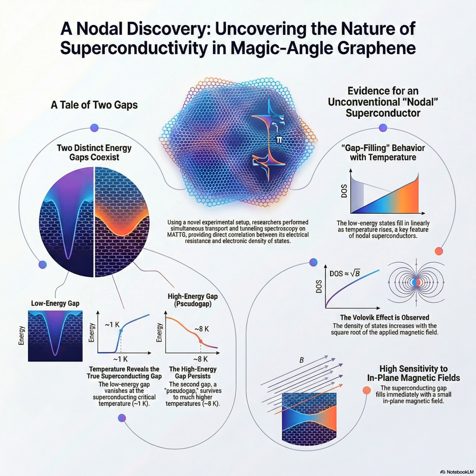Second, the research confirmed the dual nature of these energy gaps. We now know that the true, delicate superconducting engine is that low energy gap, delta SC, and that it coexists with a much hardier, higher energy pseudogap, the delta PG. And that directly connects moiré graphene physics to the really challenging high-temperature realm of the cuprate superconductors. It does. And the third, and I'd say most profound finding, is the nature of the superconducting pairing itself. It is nodal. Confirmed by the temperature behavior, and most crucially by that beautiful mathematical signature of the Volovik effect, that square root dependence on the magnetic field.